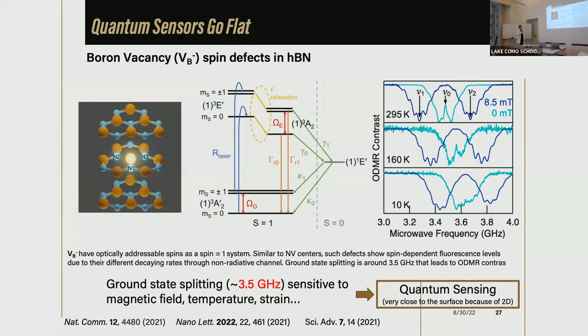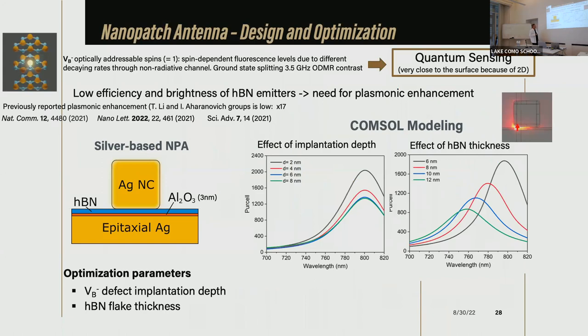It turns out that photoluminescence for a system with spin one and zero is somewhat different. It's called spin contrast. And it could be detected with optically detected magnetic resonance, ODMR. So that's very important, that you could optically create a qubit and control it for many quantum applications. And besides, of course, in this case, you have a 2D sensor, which you could bring to very close proximity of the material which you would like to probe, if you, for example, want to detect the magnetic field. So that's a great sensor for many applications.